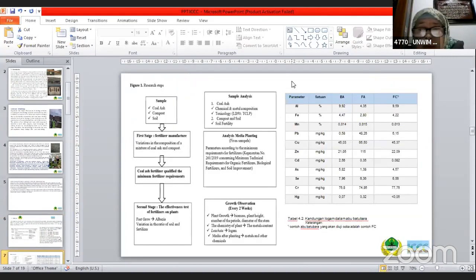The analysis parameter of TCLP: bottom ash, fly ash, and mixture. Why mixture? Because the Indominco PLTU landfill does not separate bottom and fly ash, so we made an analysis of bottom ash, fly ash, or the mix. And as can be seen in the table, the conclusion is that micro elements and heavy metals are below the threshold of the regulation of the Ministry of Environment. Okay.